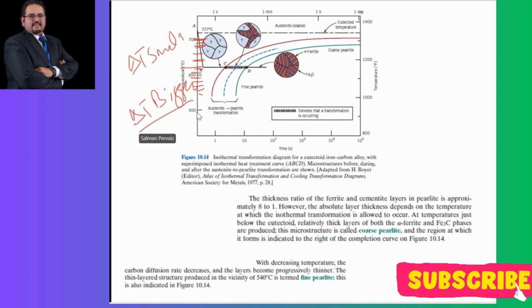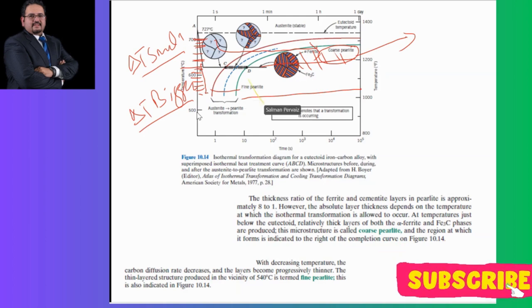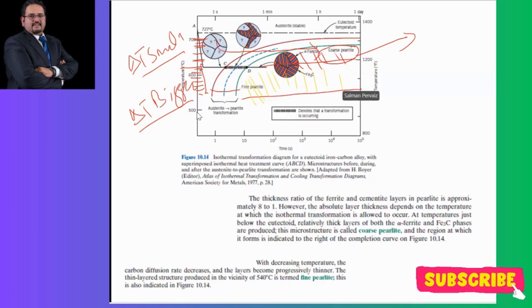So when you cross the temperature here and come on this side, because delta T is smaller, this region is dedicated for the coarse pearlite, this upper region of the diagram. If you come quickly to the lower side and cross this, then this region, the one I put with yellow lines, for example, is dedicated for fine pearlite.